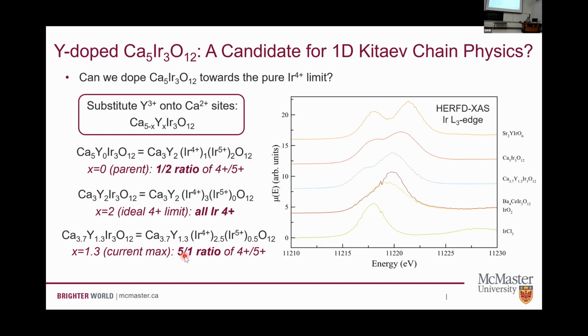Okay. If we want to convince ourselves that the yttrium is actually getting into the crystal structure, you can do single crystal refinements. Looks like it's there. Looks like it's sitting on the calcium sites where we want it. You can also do these X-ray absorption measurements to map out how the oxidation state changes as a function of doping.